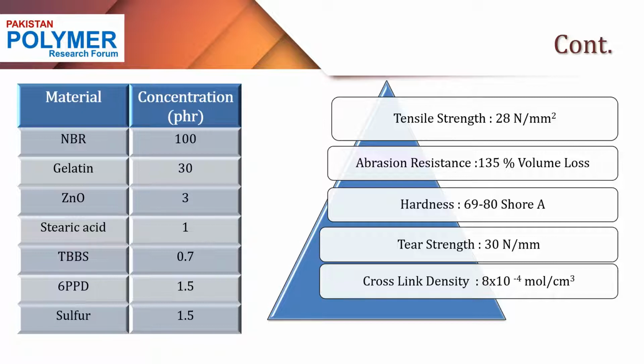From this formulation, I expect to produce an elastomer with a tensile strength of 28 Newton per millimeter square, with hardness of 69 to 80 Shore A, with the tear strength of 30 Newton per millimeter square, cross-link density of 8 times 10 to the power minus 4 mole per centimeter cube, and abrasion resistance of about 135% volume loss.